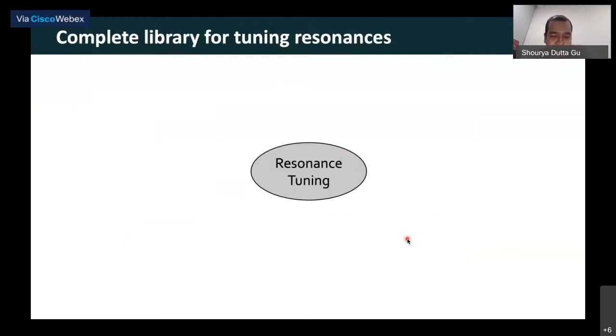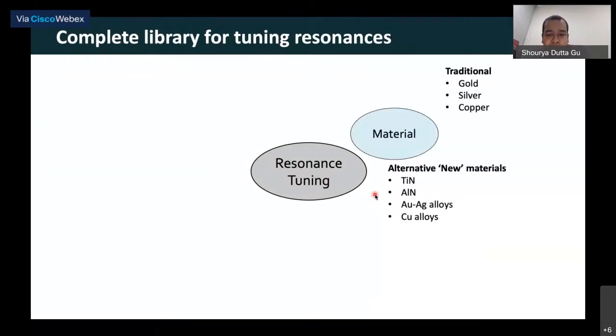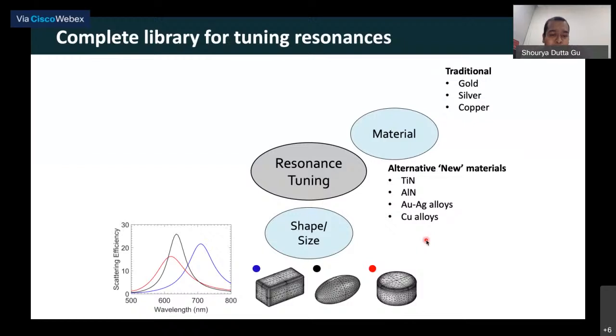Now, as I said, it's a resonant structure, right? So how do we tune the resonance? One way of tuning the resonance is to change the material. Standard materials that we work with are gold, silver, copper, all the precious metals we can think of. People have started working on new materials like titanium nitride, aluminum nitride, or alloys based on copper, silver, and gold. This is one possibility. Another possibility is, why just work with cuboids? You can change the shape of the particles, which is a very nice way of changing the resonance.